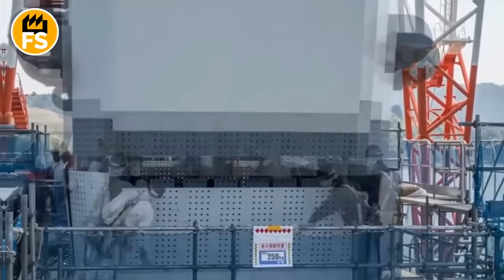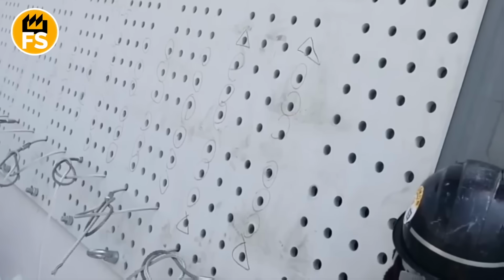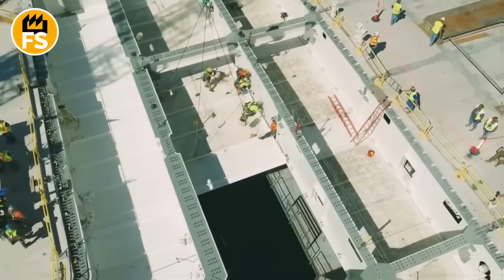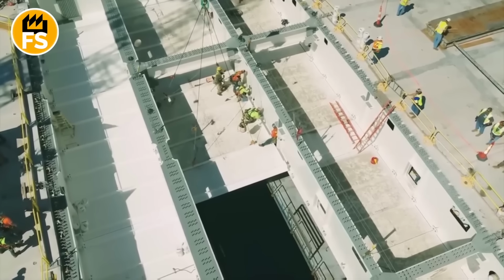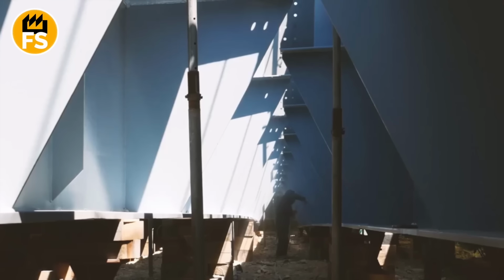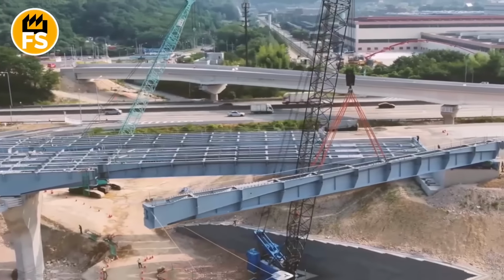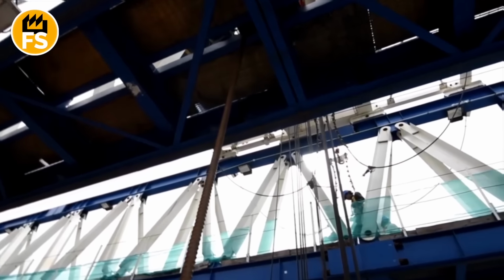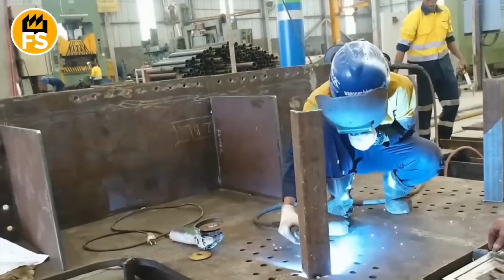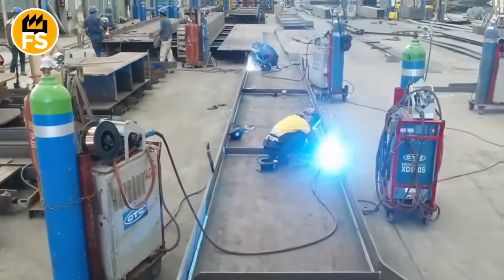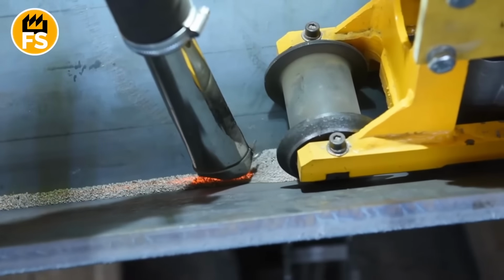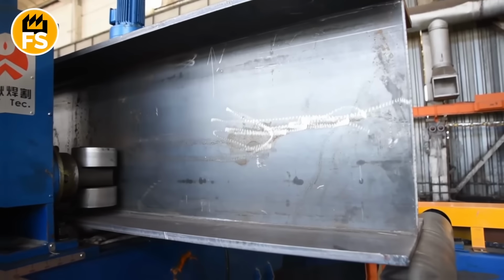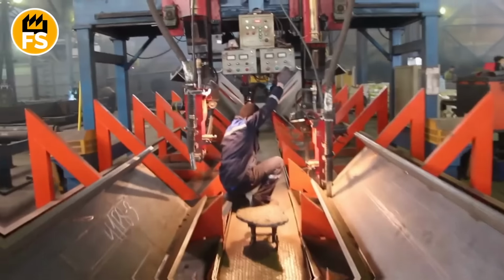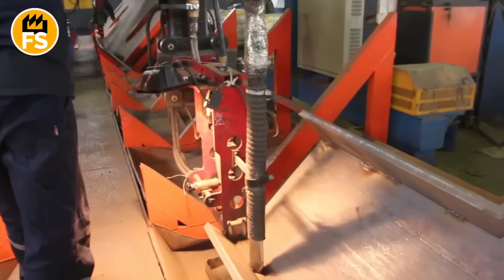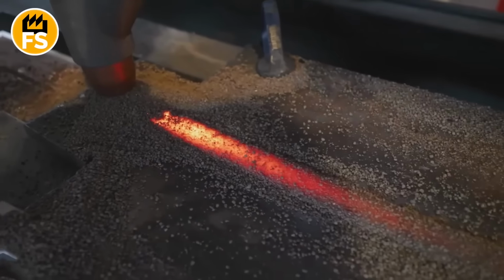Every seam, every joint has to be perfect. I walked up to these guys. They're working in special masks with fresh air supply, because the welding intensity here is so high that the air around them literally burns up. You see these welds? They're as wide as my palm. Robotic welders pass dozens of times over the exact same spot, laying down layer after layer to create a monolithic joint that no storm will ever tear apart.